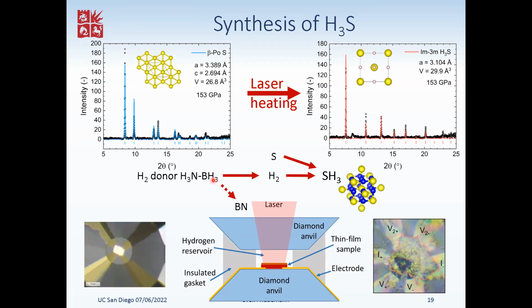Ammonia borane is actually a well-studied hydrogen donor material in the context of hydrogen-powered vehicles and fuel cells. Once you warm it up to about 70 Celsius, it starts releasing hydrogen, and it does so in several stages. First, it releases one hydrogen molecule and forms some polymer, then it releases another hydrogen and forms double-bonded polymers, and eventually it releases all of its hydrogen and what's left over is boron nitride. Boron nitride is nice and inert, so we're not too worried about this. In fact, we use boron nitride for our gasket installations anyway, so that is already present.